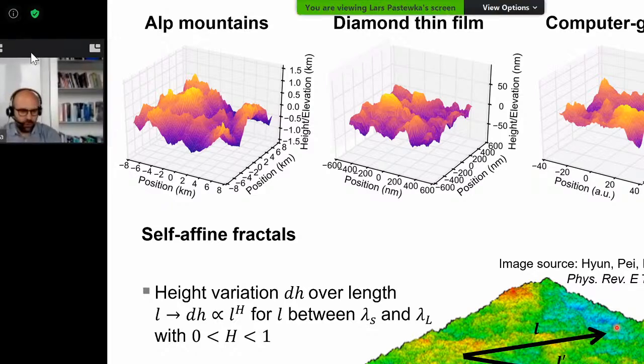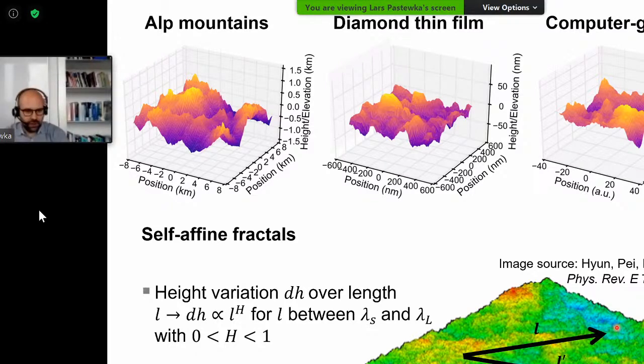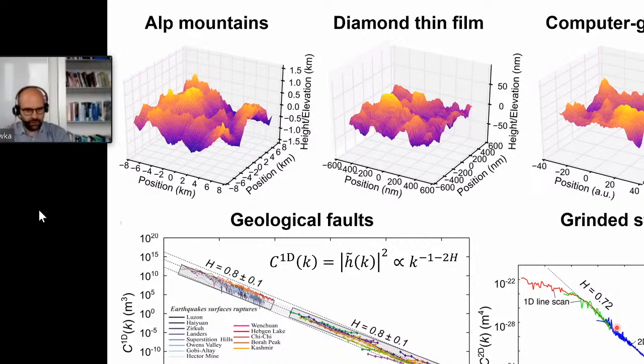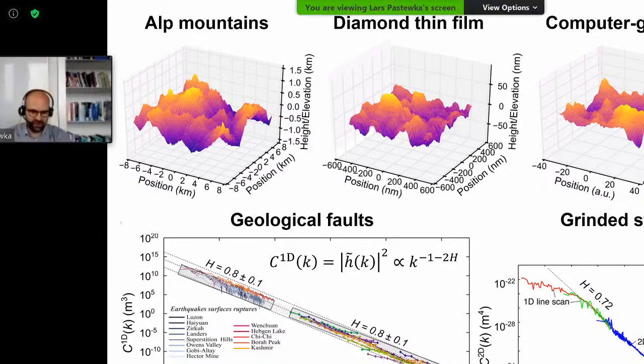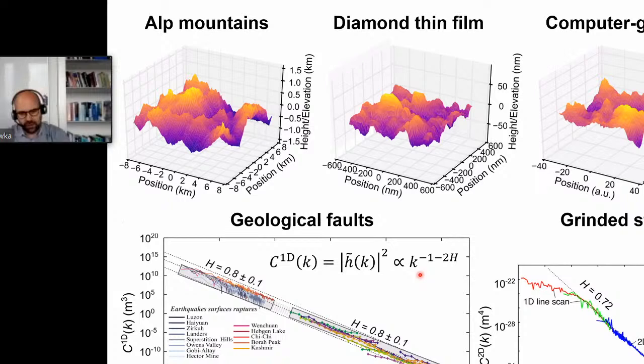So this is one way of looking at this self-affine scaling. There's different ways of detecting this. This would correspond to computing something that's called the autocorrelation function, the height difference autocorrelation function on the surface. What we can also look at, and what's more common, is looking at the power spectral density. So this plot shows on the left-hand side the power spectral density, in this case as a function of wave number that also corresponds to the length scale we are looking at. And similar to the height differences that scaled with L to the power of H, here we find power law scaling with a wave vector to the power of minus 1 minus 2H, and this is an indicator for self-affinity.